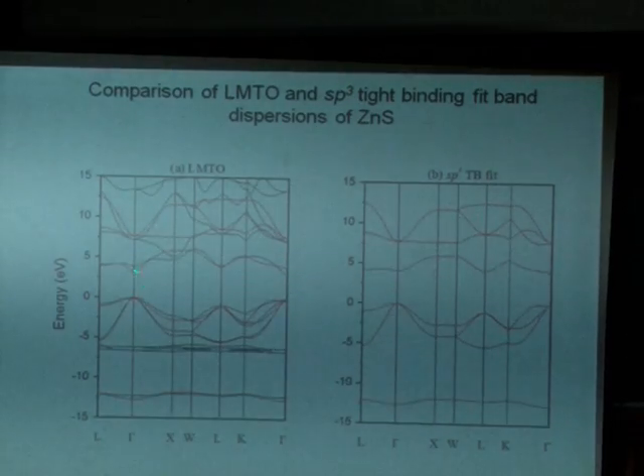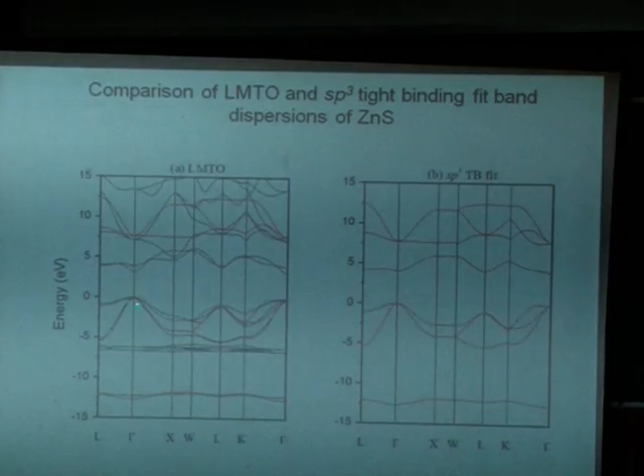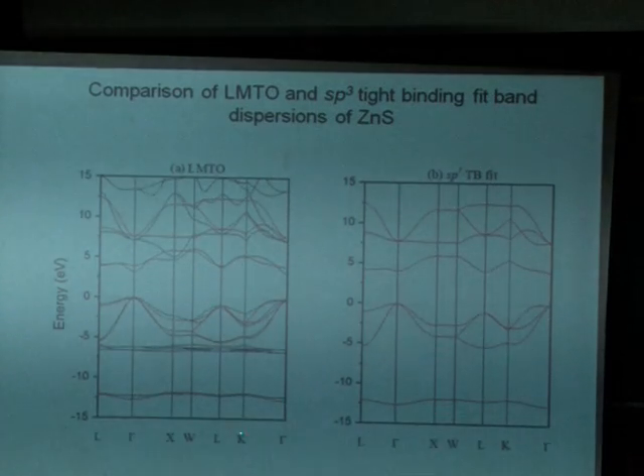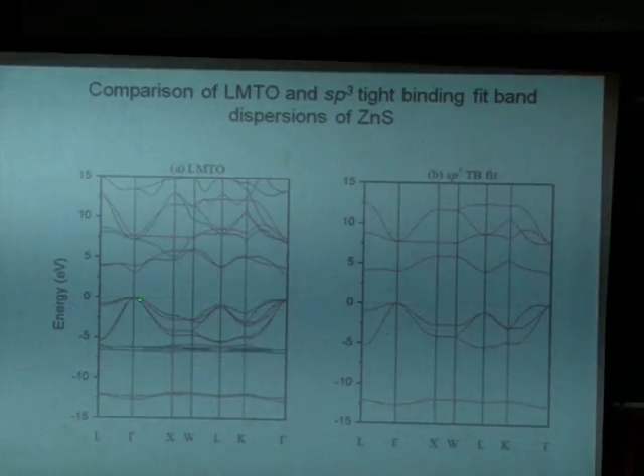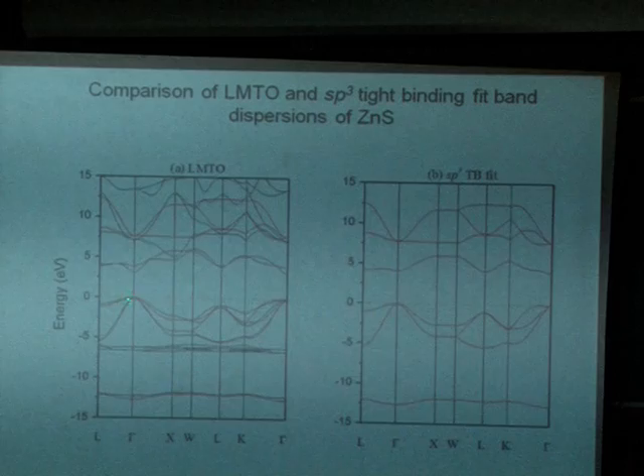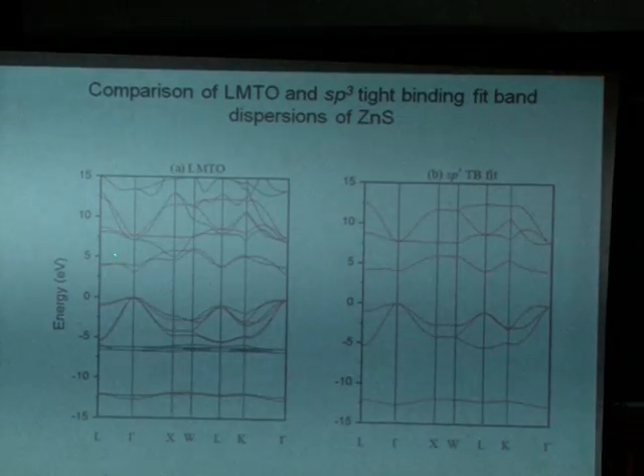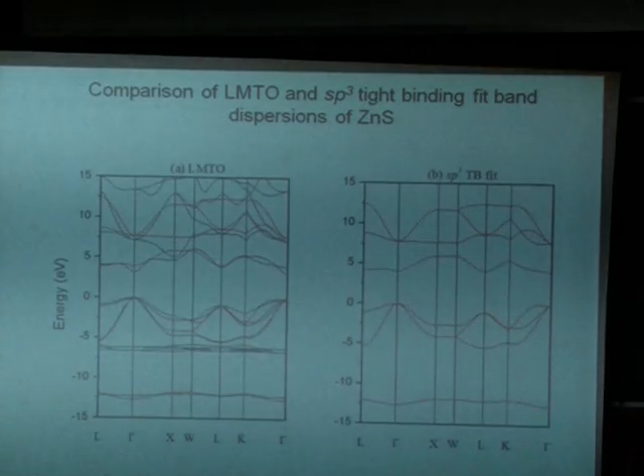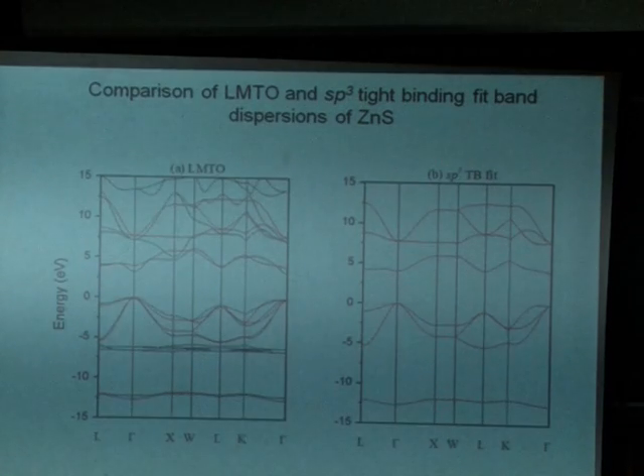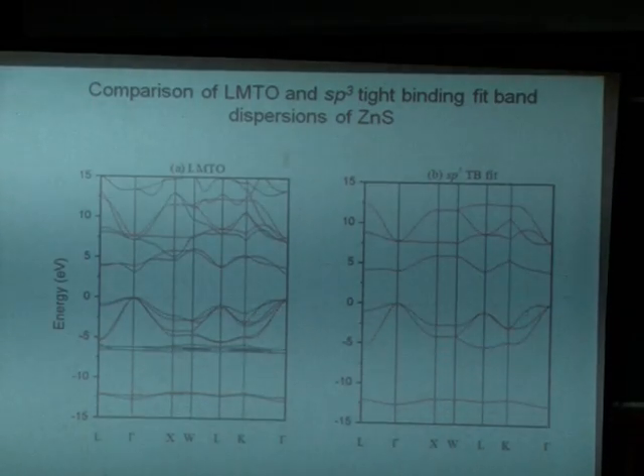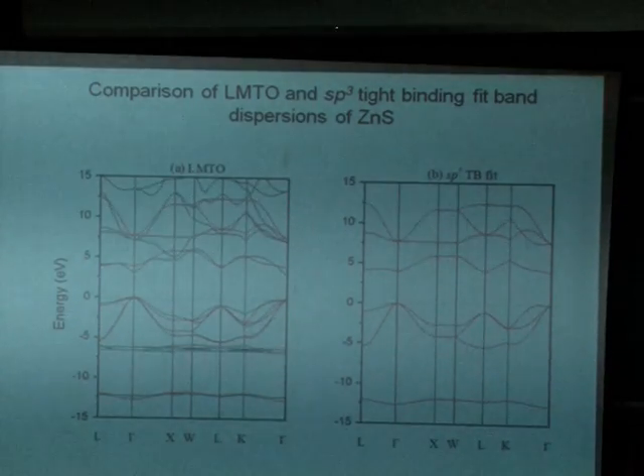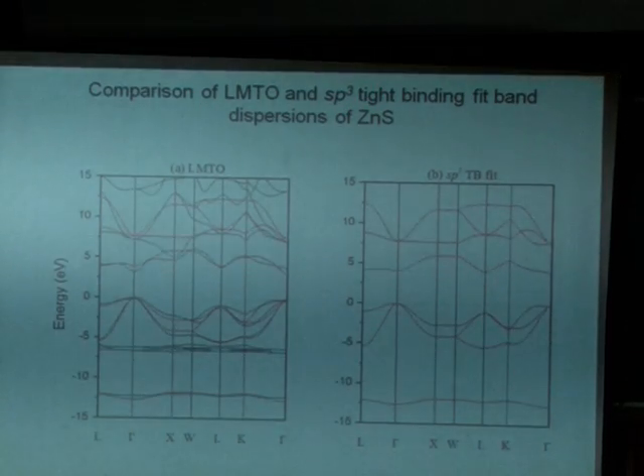And the band gap is defined here. These are the lowest energy states, all occupied states. These are all unoccupied states. And the band gap, the lowest energy gap, is here. And that part is not getting simulated correctly, which means we are doing very badly. We need to get the band gap part right. So that means that the model that we defined was not good enough.